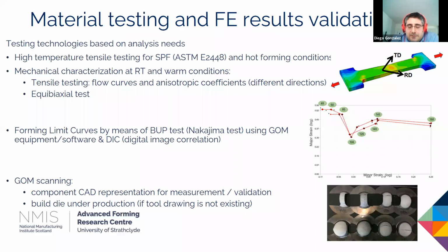Obviously, the type of tests we do are based on the analysis needs. If we work with cold technologies, we will proceed with tensile testing, for example, in order to define the flow curves, to define the R values, the anisotropic coefficients. This is also available for warm conditions. If we work with SPF processes or hot forming processes, we will proceed with tensile testing at high temperature in order to capture the rate dependence of the material on the temperature.